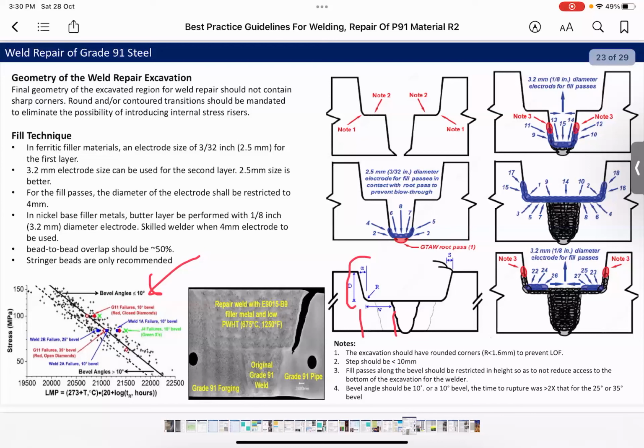So a 3.2 mm diameter electrode can be used, but we should ensure that skilled welders having good experience in P91 welding are deployed for this job. The overlap between the beads should be at least 50%, and weaving is not allowed, for reasons related to high heat input and thicker heat affected zone in the base metal, which can make the weld or the heat affected zone susceptible to cracking during service.